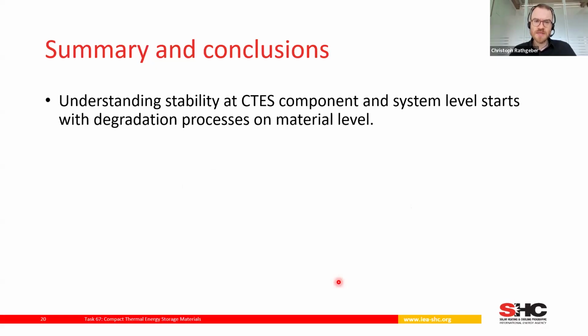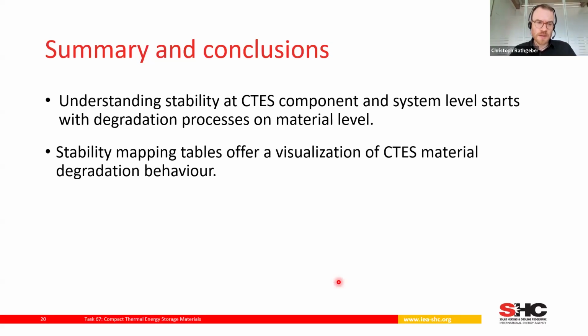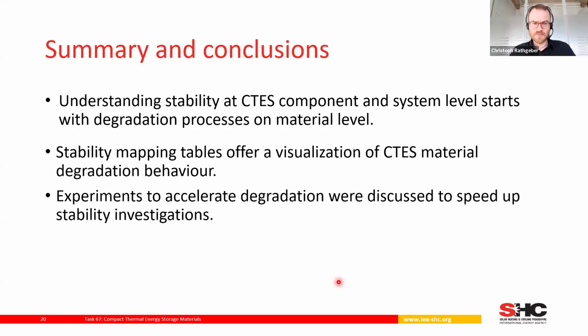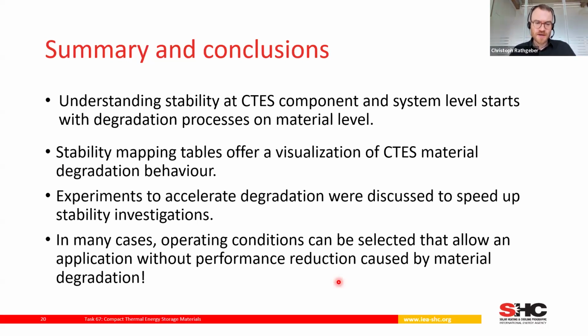We see that understanding the stability of CTES on component and system level starts with the degradation processes on material level, so on the very basic material research level. And then we worked on stability mapping, and this offers a useful visualization of CTES material degradation behavior. And we also talked about experiments to accelerate degradation, and they can be recommended to speed up stability investigation. Well, so to end with a positive statement, we also have to say that in many cases, really many cases, operating conditions can be selected that allow an application without a performance reduction caused by material degradation.